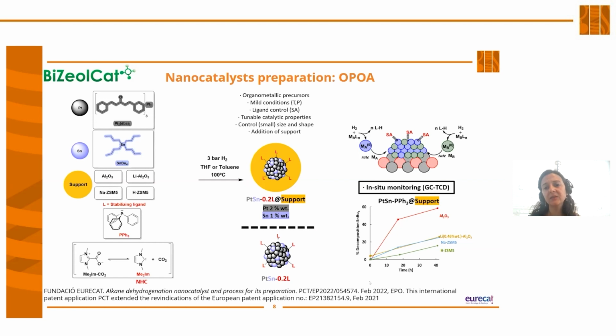In this case, both the ligand and the support control the decomposition of these metallic precursors, so we can have a very controlled nanoparticle with very controlled properties. We can monitor this reaction by GC by looking at the butene that comes from the decomposition of tetrabutyltin.